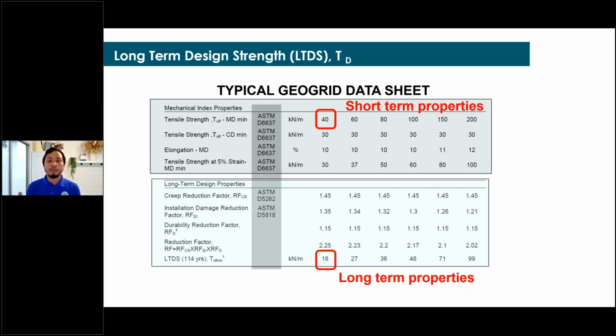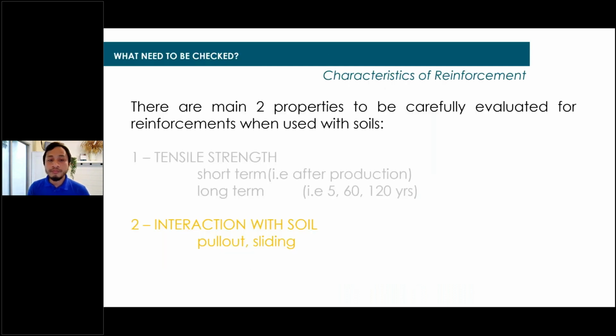Now, this is just to illustrate what I mentioned just now, the long-term design strength. You can see here 40 kilonewtons. After the reduction factors, you will only get 18 kilonewtons. So this is very important. You do not want to use that 40 kilonewtons for the analysis, or you will end up with an overestimate of the safety factor when you check the stability of the slopes or the walls.